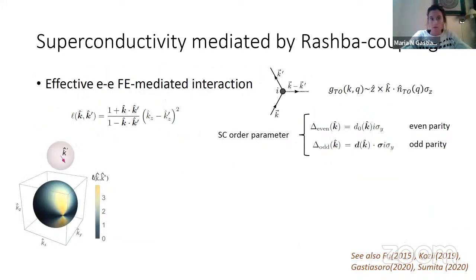And then I have my expression for the coupling, so I can play the usual game. I convert into an effective electron-electron interaction, just like I do with a conventional electron-phonon or with a spin fluctuation mechanism. I have a vertex that is now a little bit different because it has a sigma z. That's definitely different from a phonon, and then it is proportional to K. But I derive the interaction is going to have some momentum dependence, again because my vertex is momentum dependent.